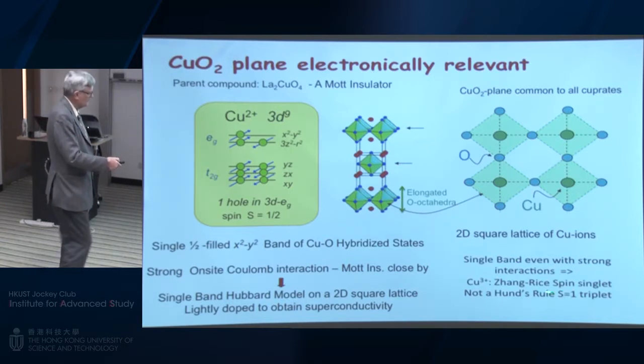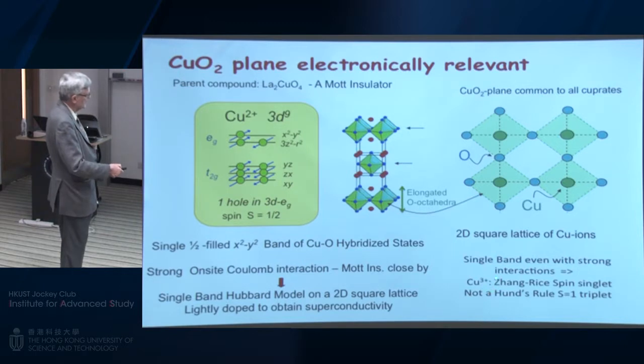as was mentioned in the introduction, a paper with Fuchun Zhang soon after these materials were discovered showed that even in the presence of strong interactions, this state, when we take an electron away, copper 3+, is still a spin singlet and not a Hund's rule triplet, which we might have expected, because if we take one away, we could have had 2 electrons in 2 different orbitals. Instead, the electron comes out of the same orbital. So this makes any holes or any extra electrons that we remove very mobile. And so we have a material which has a single isolated band here at the top of the anti-bonding bands between the copper and the oxygen, which is nearly half filled. As we dope it to get the superconductor, we remove electrons, or as we say, dope holes into this material.